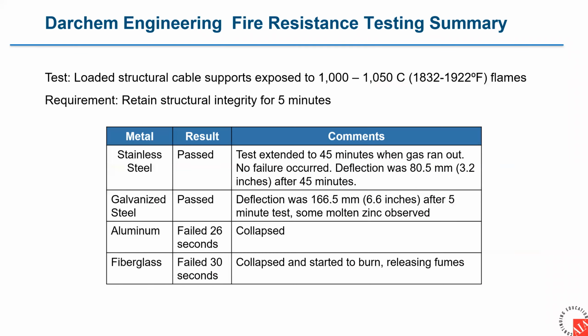So the data for that test, which was conducted over 30 years ago, as the result of a North Shore fire platform, is summarized on this slide. Of course, the aluminum and fiberglass failed quickly. That's not surprising because they're low temperature melting materials.